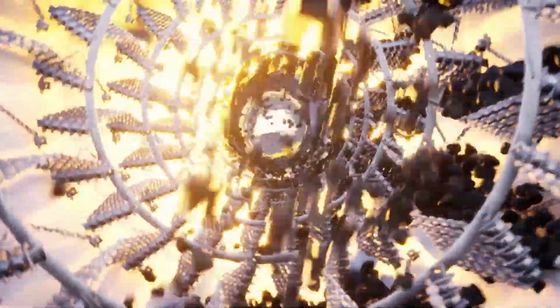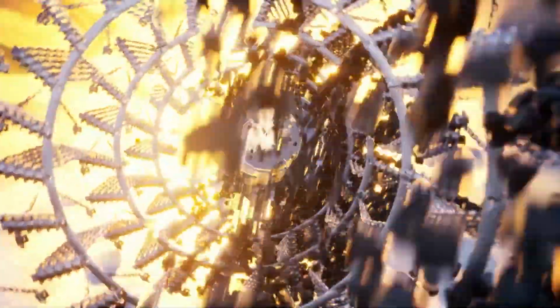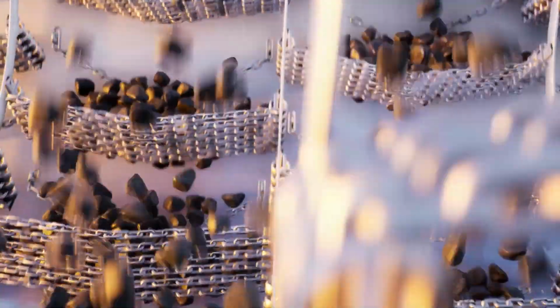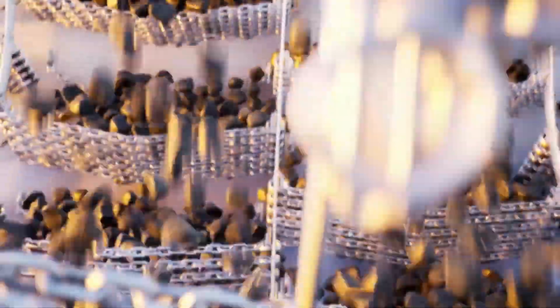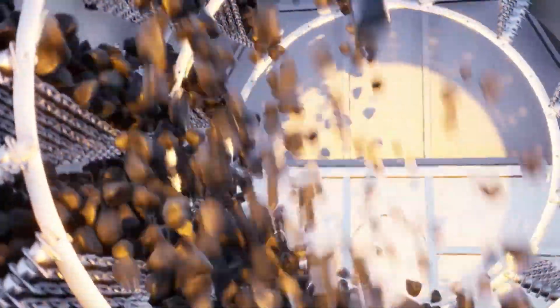Our RAP pellets are in full contact with hot airflow to achieve heat exchange and reach the required temperature. The reclaiming drum is composed of chain structure blades that are densely and evenly distributed, and the RAP forms a wide and thin material curtain inside the drying drum. Heat is fully exchanged between our RAP and hot airflow. Flexible bionic technology and the flexible lifting curtain allow the drum to be self-cleaned to effectively prevent sticking. The hardness of the chain is up to HRC 50 after heat treatment.